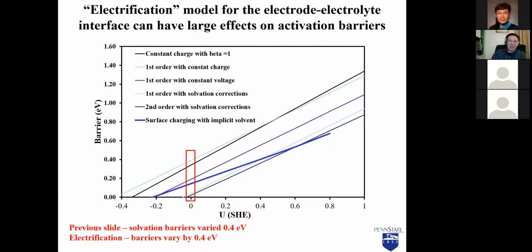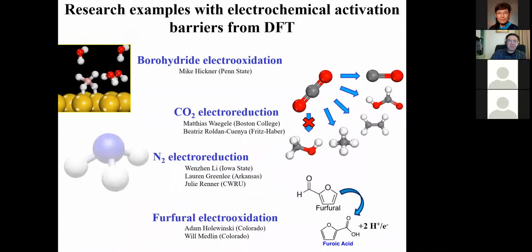I should highlight these are not additive, because solvation had to be in here, because when we electrify, we then often also have to solvate. But they are somewhat additive. So barriers can vary on the order of 0.6 eV based on the approach used to calculate them. With that, we've still been able to use computed barriers to help us understand a number of different applications.